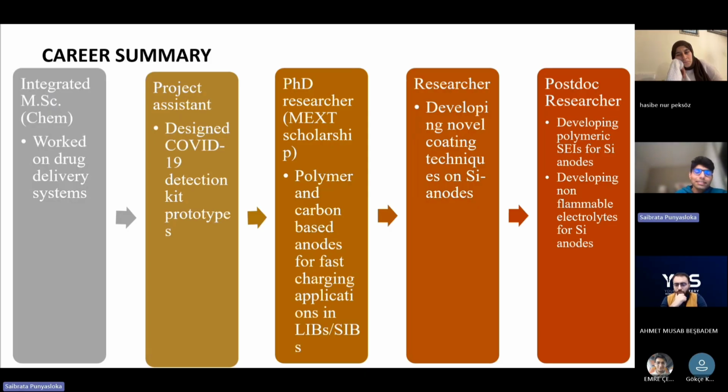And if excessive electrolyte reduction is not taking place, our battery can perform longer. So that is the basic idea of having an artificial polymeric SEI on top of the anode itself. That is one of my projects, which is quite challenging because it's very difficult to suddenly have a polymer, because polymer as such is non-conductive.